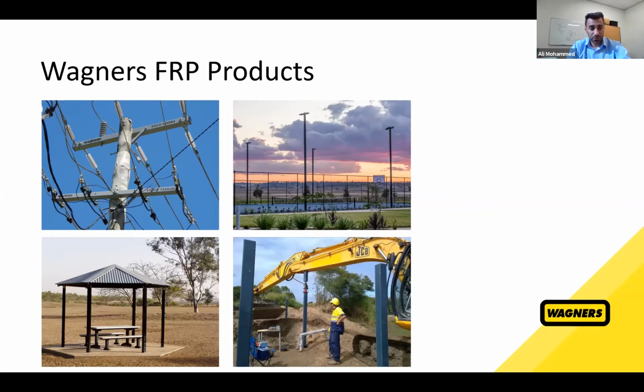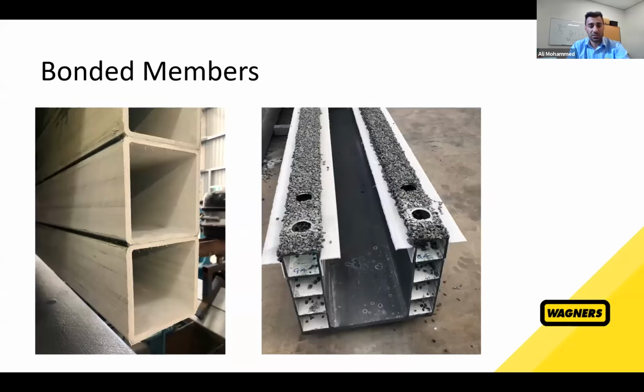So all these products require minor finishing, minor modification on the surface to suit that specific application. For example, for the cross arms, we need a special surface treatment to give it the proper electrical properties, and this kind of surface treatment is not required for the pile, and it's the same for every single application. In addition, these individual sections can be assembled together, as we can see in this photo, where several structural sections have been bonded together, forming bigger sections and achieving higher strength and higher stiffness.